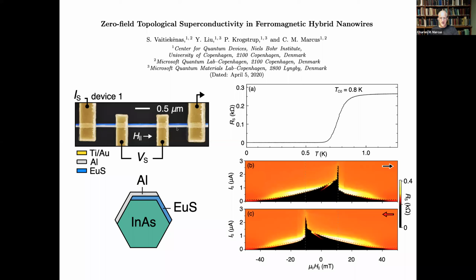What you see is that above a temperature of 800 millikelvin, the material is resistive. The aluminum is resistive. This is just a 4-wire measurement of the full nanowire. Superconductivity in the aluminum is destroyed above 800 millikelvin. Below 800 millikelvin, there's a smooth transition to a superconducting state. In this superconducting state, at the lowest base temperature of the dilution refrigerator, if you try to apply a current, you can find that there's a critical current above which the resistance turns on. Below it, it's zero resistance, and above it, it becomes resistive.